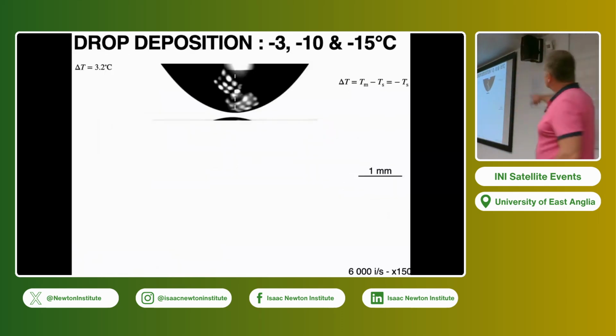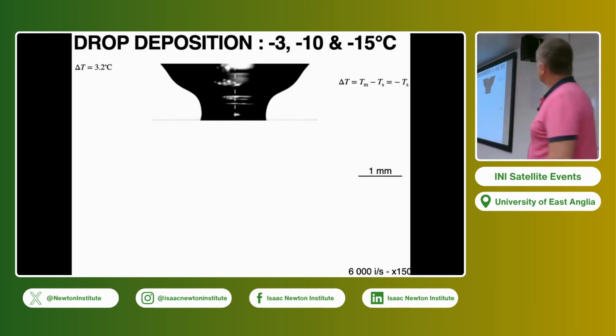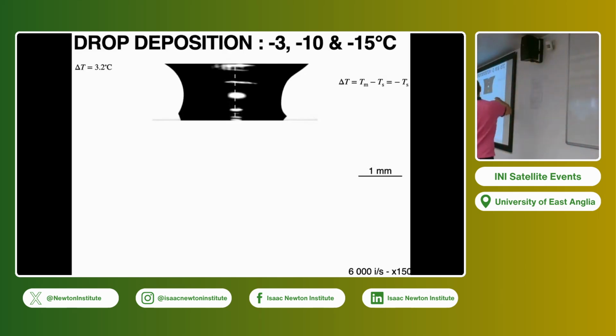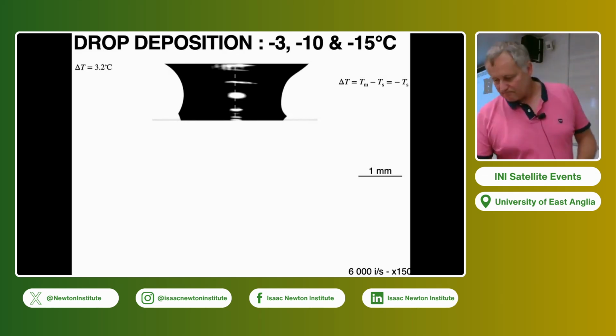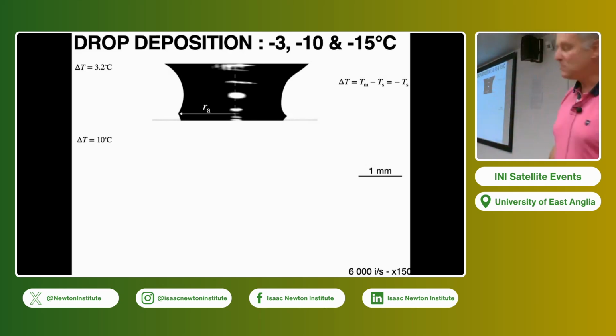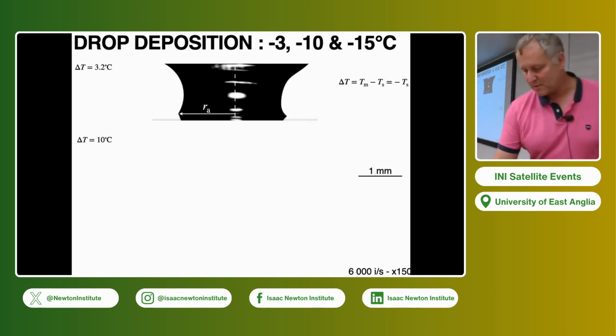Okay, so delta T is my undercooling. If I have delta T equals 3.2, that means that my sapphire is at minus 3.2 Celsius degrees. You see, the drop is spreading, and at some point it stops. This is the maximum radius. It has reached a radius at which it stops. We can measure the radius of the contact line as a function of time, and particularly the radius RS, I mean the maximum radius, or the radius at which the spreading stops.